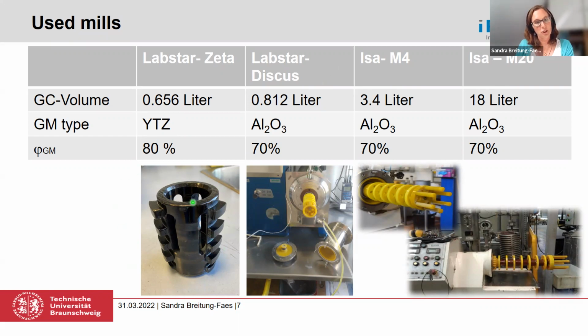On the one hand side, we have the Zeta geometry, which was developed by Netzsch, I guess, at the beginning of the 2000s, especially for nano grinding applications. You see, it's not the typical discs. It's something like pins, and you can see these holes in the rotor, which are there for the separation of very small grinding beads. This mill has a grinding chamber volume of a little bit more than half a liter, and I used it for many of my experiments, especially for the different materials in nano grinding. And as was usual for nano grinding applications, I used zirconia beads because they were said to be very wear resistant and available in very small sizes.